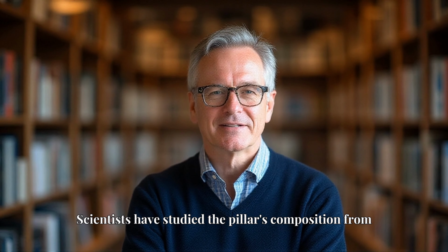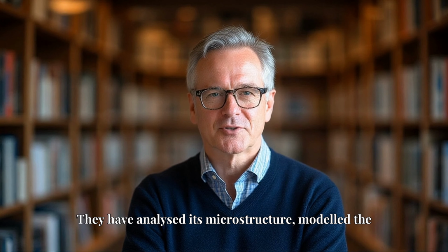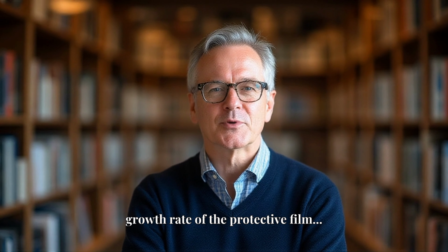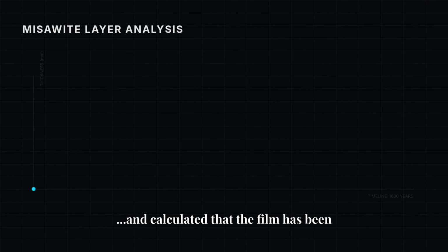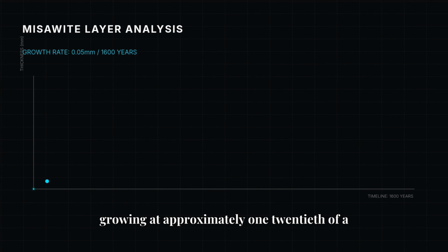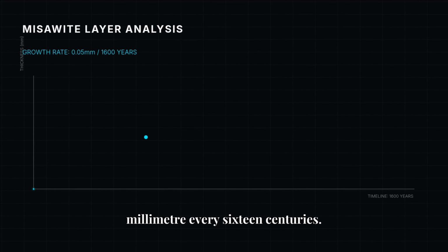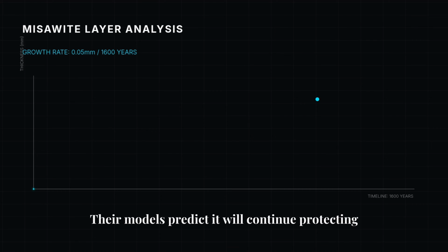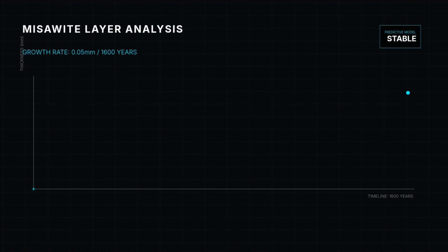Scientists have studied the pillar's composition from multiple angles. They have analyzed its microstructure, modeled the growth rate of the protective film, and calculated that the film has been growing at approximately 1/20th of a millimeter every 16 centuries. Their models predict it will continue protecting the iron for the foreseeable future, possibly indefinitely.